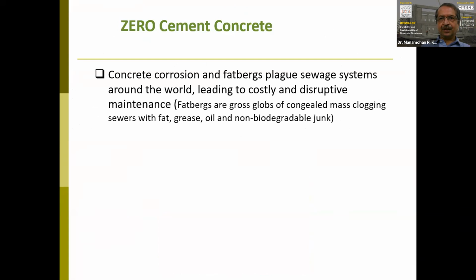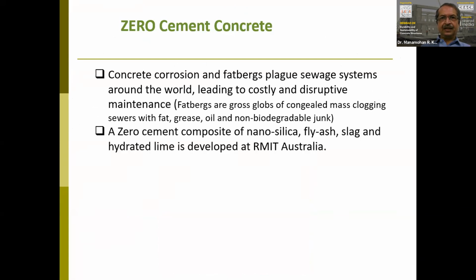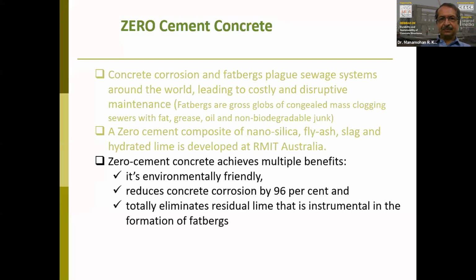This is again from Australia, and this is for concrete corrosion avoidance in the sewage systems by using this particular cement, which is a composite of nanosilica, fly ash, slag, and hydrated lime. So this is something which they are trying to push and see. They are saying that it can reduce concrete corrosion by 96% and totally eliminates residual lime that is instrumental in the formation of fatbergs, which are very common in sewage systems.